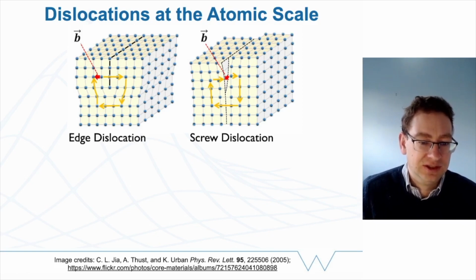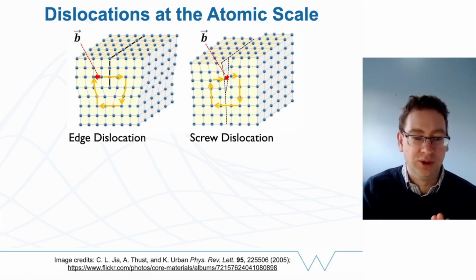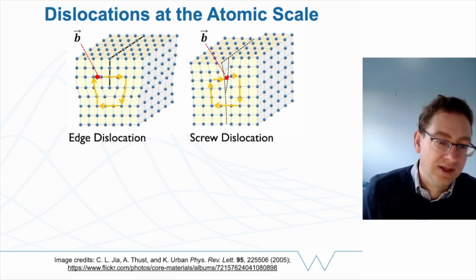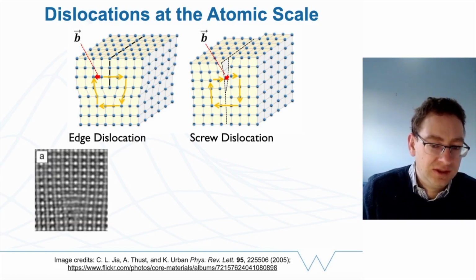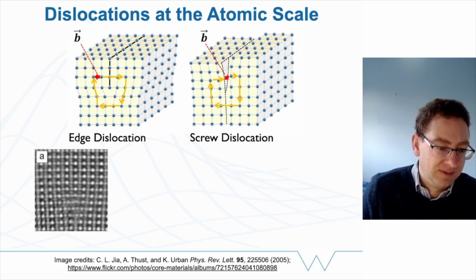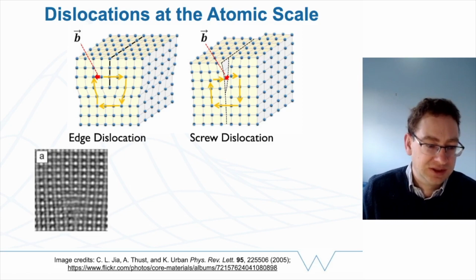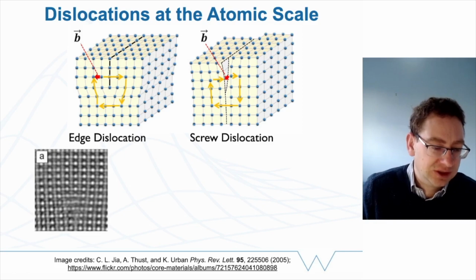The other type of dislocation is a little bit harder to visualize. That's called a screw dislocation, and that's where the shift is instead in the other direction, the out of plane direction, and the atoms instead have a mismatch in that they've been pushed backwards on one layer. If we look in real materials, we can find very good pictures. This is a microscopic image of what an edge dislocation really looks like, and you can actually resolve the individual atoms. This is a transmission electron microscopy image, TEM image, and you can really see the atoms that form this